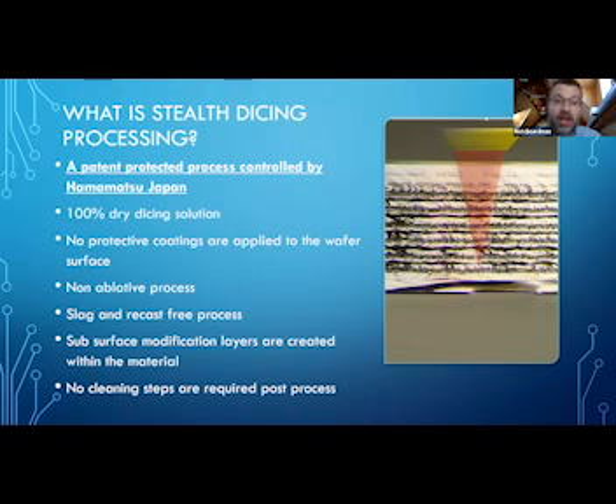So in a nutshell, what is stealth? It's a 100% dry laser singulation process. It's not an ablative laser process. With laser ablation, it is necessary to deposit a coating on the surface of the wafer. You focus the laser light on this top surface of the wafer, and slag and recast and debris is created. And then downstream, before the wafer is removed from the laser saw, you have to do a wash step to remove that protective coating. For devices that are sensitive to water or debris or slag or recast, that laser ablation process is not a good fit. And this is where stealth really comes in.